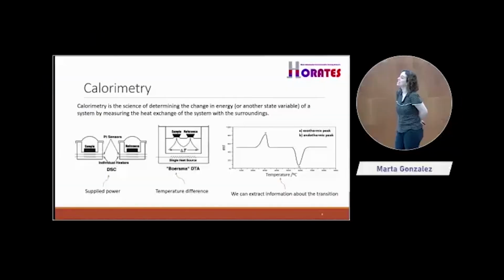The thing is that I didn't say that because it has a lot of things behind it, okay? But the thing is that here you get the power you provide. But it's not a direct measurement of CP. To get CP, you have to calibrate the system very well. That's one thing. The second thing is that in principle this is flat, but this is fake. In principle, if you are accessing CP, even if it's not CP directly but power, you should have a certain ramp, because you have to provide heat to heat up the system. Yeah, exactly. It's a feedback. That depends a lot on the reference you're using. If the reference has a similar CP but with no transition, then you will have a flat thing because you're comparing the two. But if you had just one, you should have a certain ramp. But it's all a matter of calibration. The baseline is a nightmare. Okay, yeah, thanks.